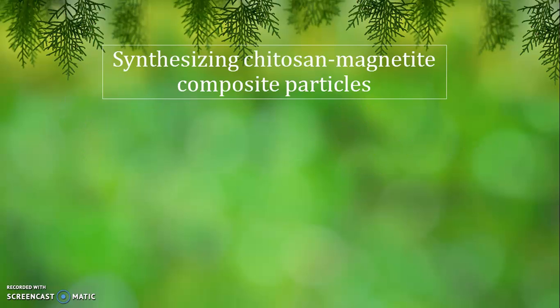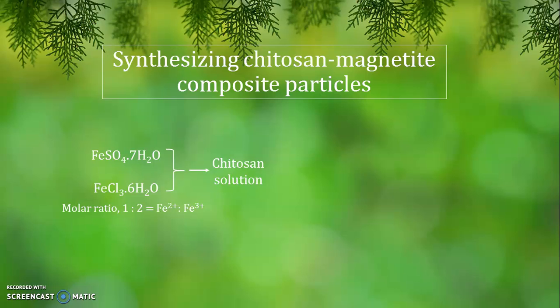Synthesizing chitosan-magnetite composite particles. This method will begin with two solutions, which are iron 2 sulfate and iron 3 chloride, by using molar ratio 1 to 2, and this solution will be mixed together with chitosan solution. The chitosan solution means the chitosan has been dissolved in water, and these three solutions are mixed and start the co-precipitation process by adding sodium hydroxide dropwise.